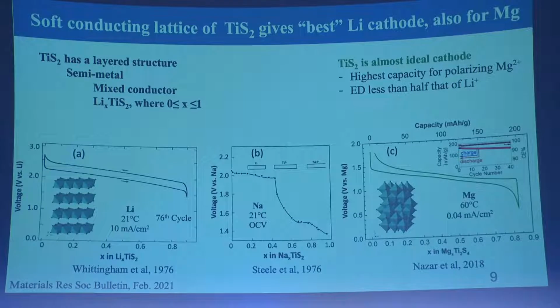And on the right-hand side, I'll show you the picture for a magnesium battery, and this is work by the Canadian group. And what they found out is it's a good metallic conductor. That means the charge on the magnesium is shielded. It's a soft lattice, so the magnesium ions can diffuse in and out. But again, look closely at the numbers. This is operated at 60 degrees centigrade compared with room temperature, and it's operating at 0.04 milliamps per square centimeter, not 10. And the voltage is about 1 volt lower than the lithium batteries.